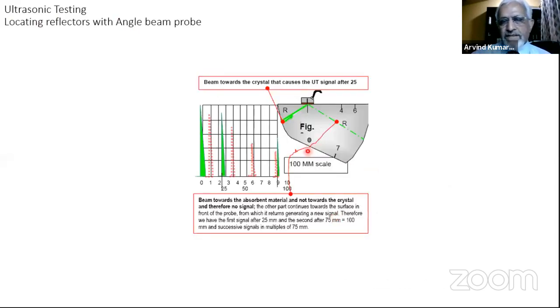Like here, there is a 25 mm and 50 mm, no, 25 mm and 75 mm. So here it is explained also: the first peak comes from 25, the second comes after 75, that is 100, and after each multiple of 75, the next will come at 175, then 250, like that.